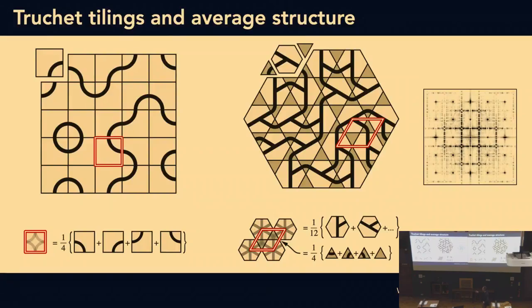But if you take one like this one on the left, and you say I did this on the atomic scale, our way of characterizing it would be to use crystallography, to use a diffraction experiment. And the diffraction pattern for something like this looks like what you see on the right. It's the sort of diffraction pattern that we're used to interpreting in this world of order. It has a set of Bragg reflections, these repeating spots, that capture the underlying periodicity of the tiling.